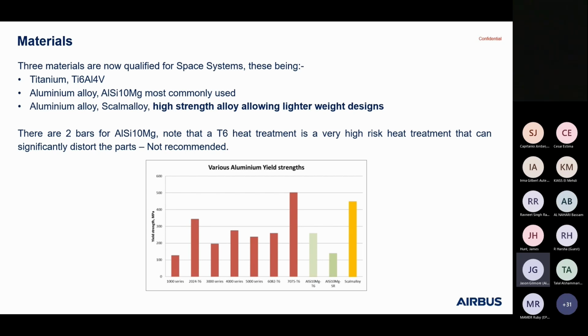So in the qualification, everything was near the 500 mark. And then there's a knockdown factor for scatter between batches. We've declared 450 megapascals. So that now enables you to really lightweight designs compared to an aluminium silicon 10 in a stress relief condition. Next slide.